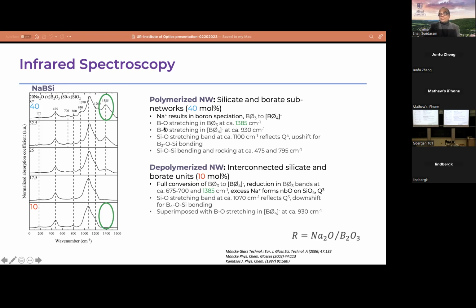That band corresponds to boron oxygen stretching in borate triangular coordination in the glass. And you can see I will also point out other features later as we go down here. So if you look at the 10 mole% depolymerized borosilicate glass, you can see that 1385 is barely present here, and that this structure is dominated by silicon oxygen stretching bond and other bonds we see here for this depolymerized structure.